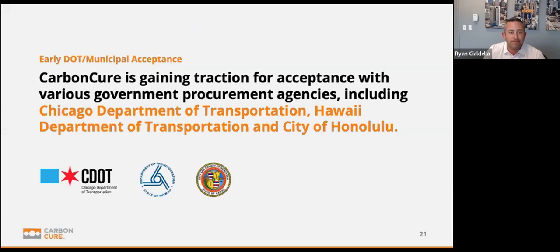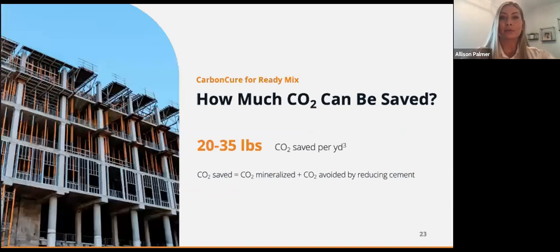Great. Thanks, Ryan. So how much CO2 can be saved? At the end of the day, this process reduces approximately 25 pounds of CO2 per cubic yard of concrete. This figure can vary quite a bit depending upon the mix design, but one way we see these reductions is through that 1 pound of CO2 that's injected into the mix, converted to a mineral and permanently sequestered. But the majority of the carbon savings really come from the ability to reduce our cement content.